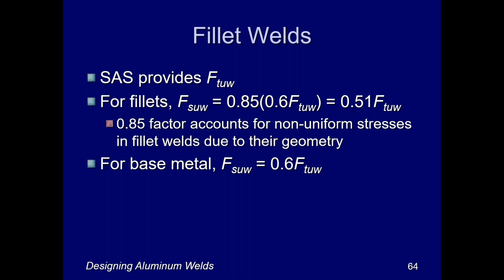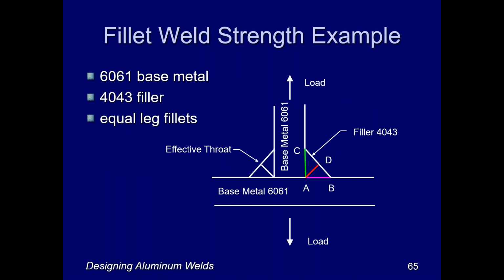So you get the tensile ultimate strength of the filler metal from the specification for aluminum structures. And for the fillet weld, then we're going to take 85% of 60% of the tensile strength, because remember, the shear strength is 60% of the tensile strength, and we consider shear to be acting on fillet weld throats. Therefore, that works out to be 51% of the tensile ultimate strength. For base metal, we don't have that 0.85 factor because it doesn't have the stress riser that the fillet material does, and so it's just 0.6 times the tensile ultimate strength.